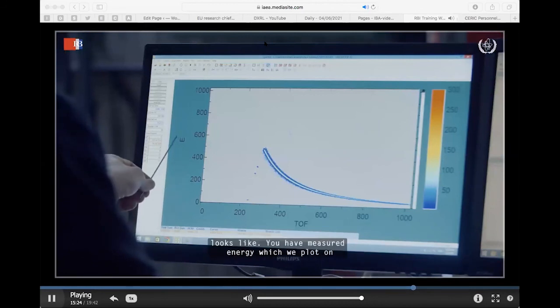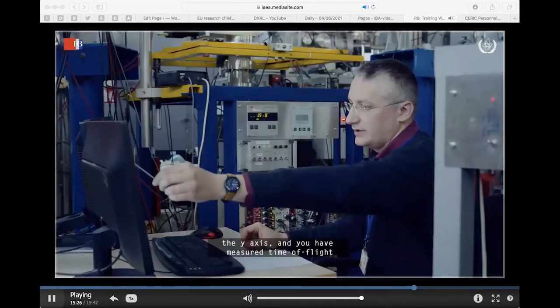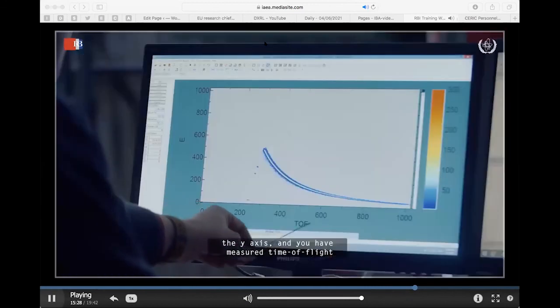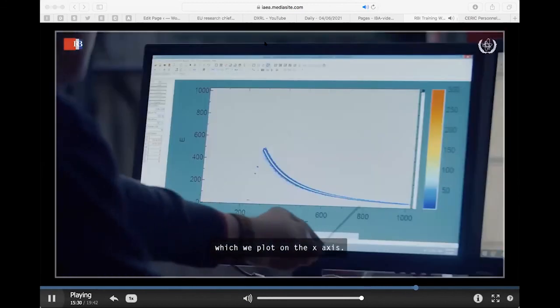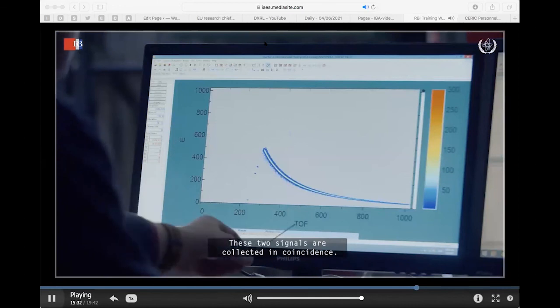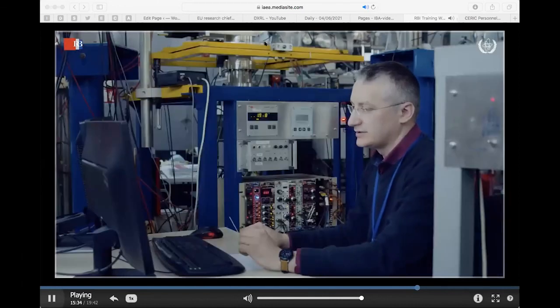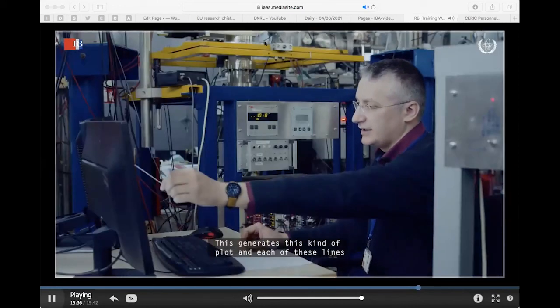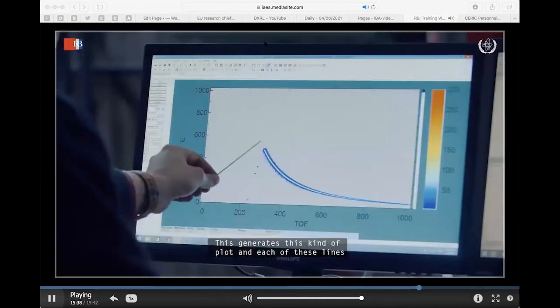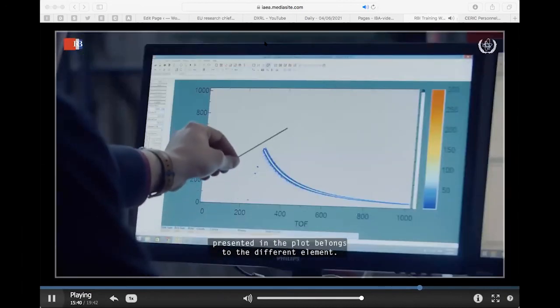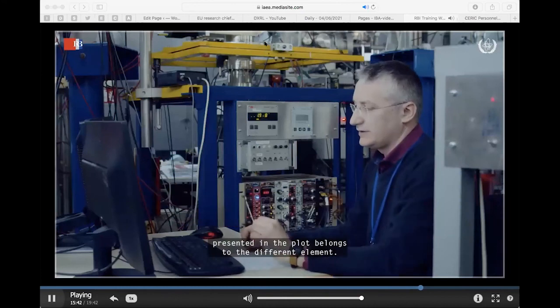You have the measured energy, which we plot on the y-axis, and you have the measured time of flight, which we plot on the x-axis. These two signals are collected in coincidence. This generates this kind of plot, and each of the lines presented in the plot belongs to a different element.